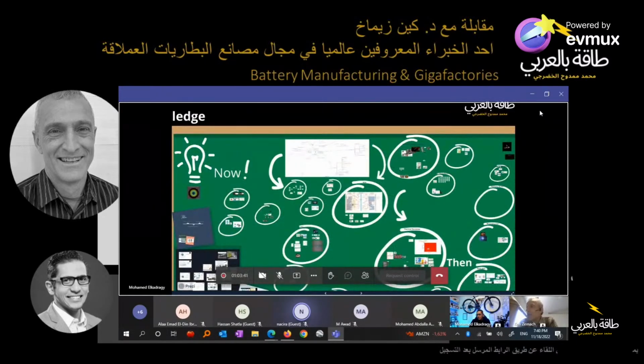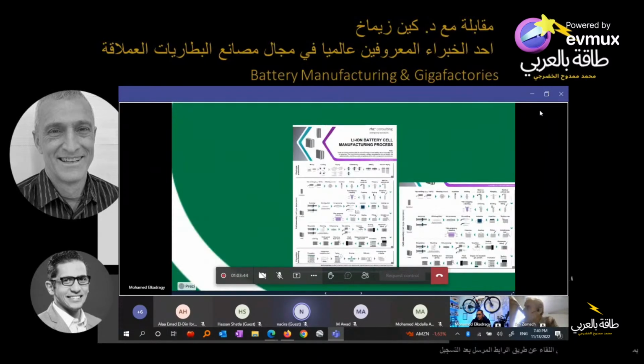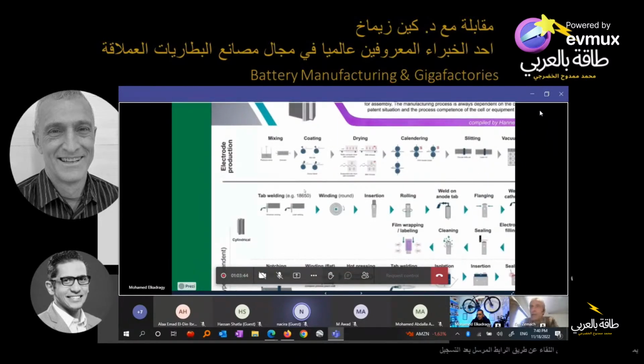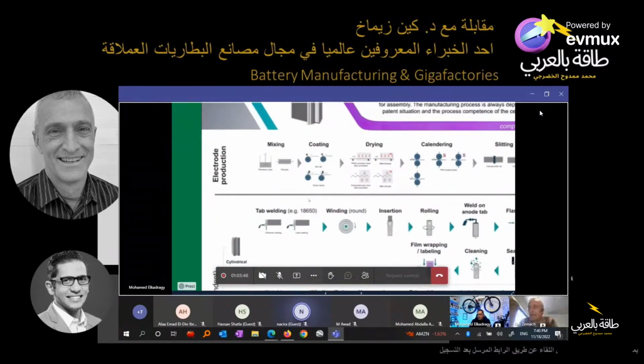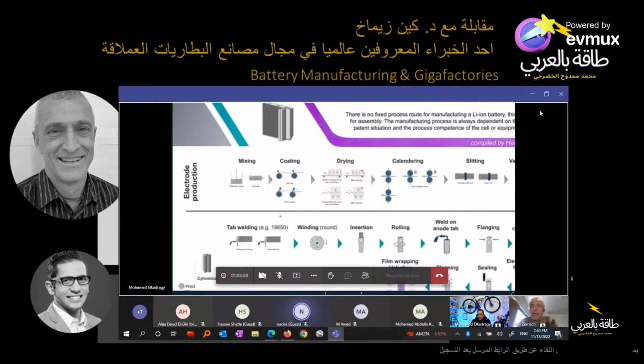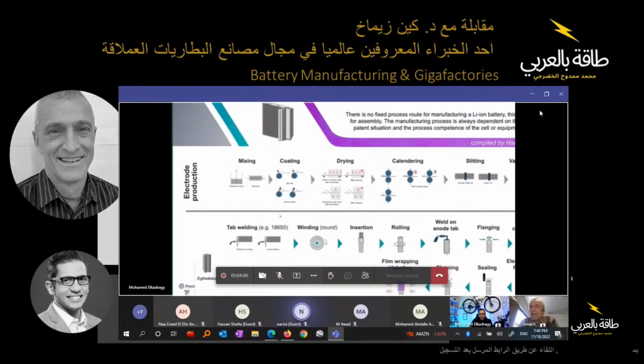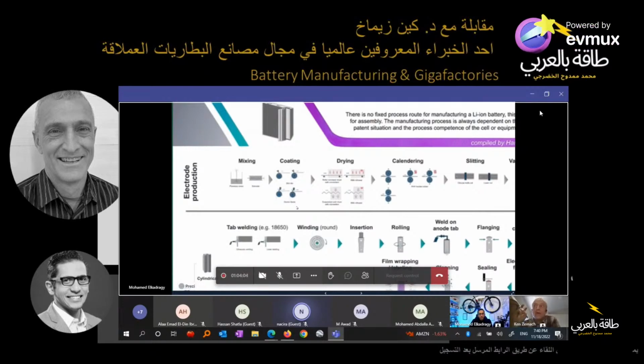I said that the anode is graphite, a conductive agent. You're talking a very little bit of conductive agent, 0.5% by weight, 1% by weight, maybe 2%. So it's primarily graphite, a conductive agent, and a binder, aka the glue. The standard glue in an anode, and again, always exceptions to this, are carboxymethylcellulose and styrene butadiene, a low molecular rubber.